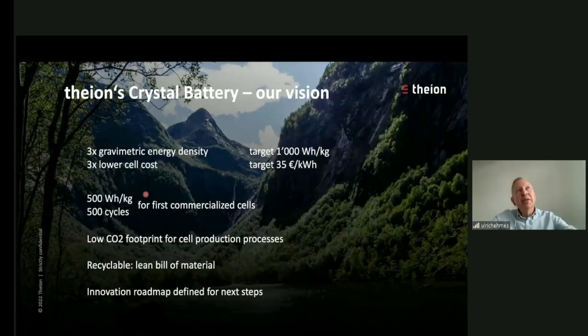But let's put this material into a cell. Our target is to achieve a 3 times higher gravimetric energy density compared to the state of the art. Today's state of the art is 300 watt hours per kg. But we have established a roadmap with improvements on the cathode side, electrolyte, and anode side to reach 1000 watt hours and to bring the cost down by a factor of 3 to 35 euros per kilowatt hour because of this cheap material.